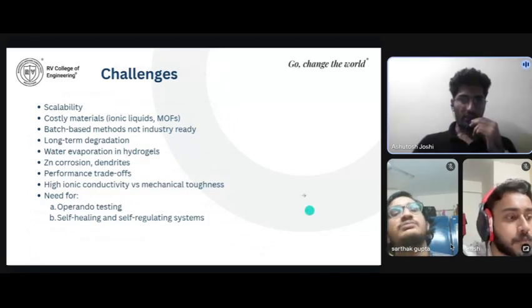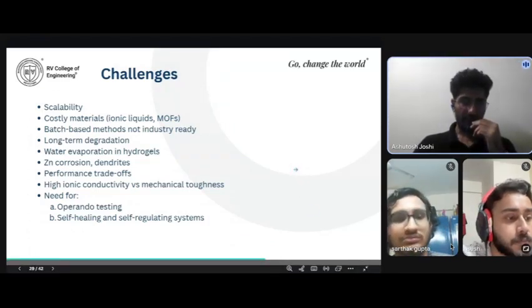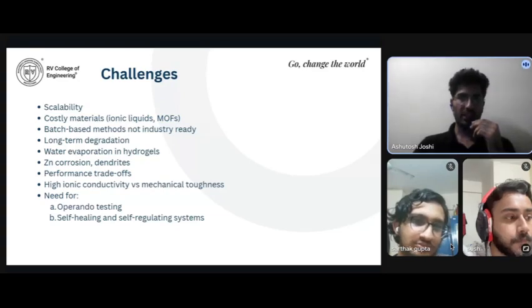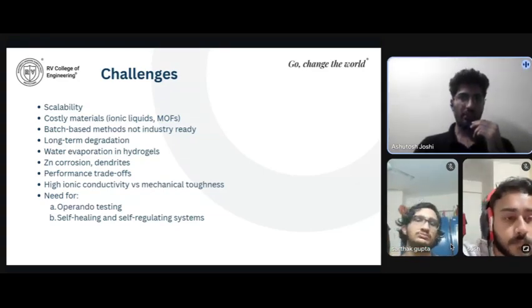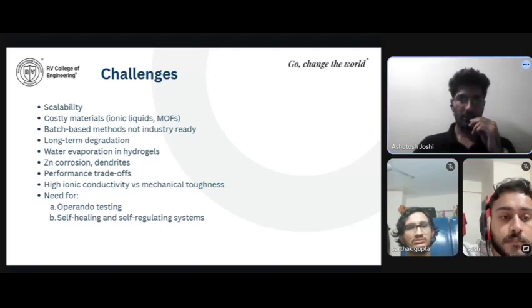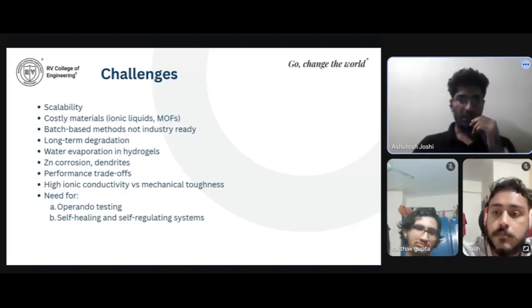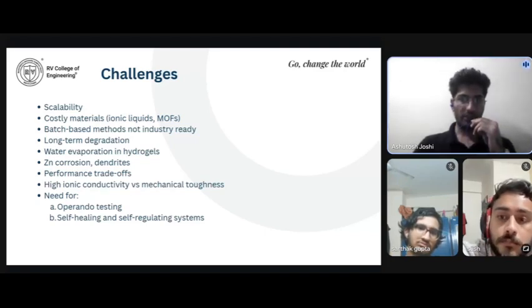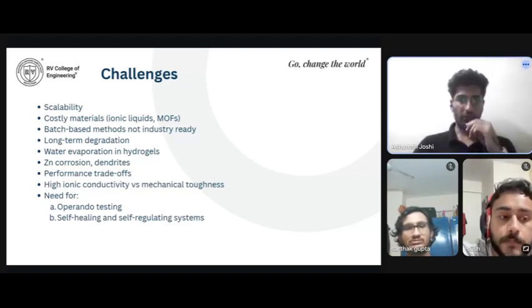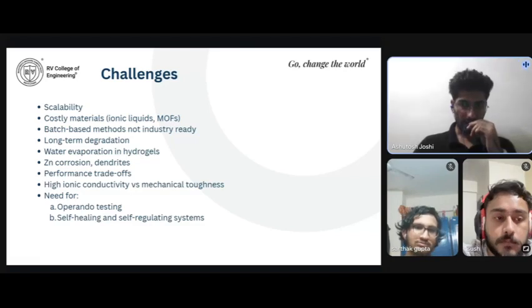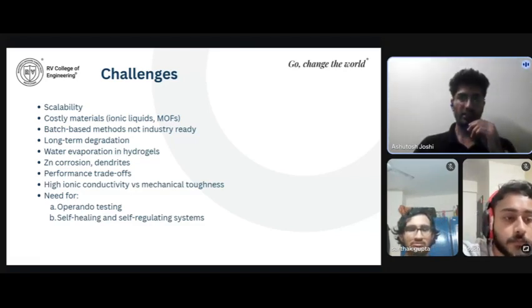So here are some challenges of QSs. First, scalability. Most QSs use expensive materials such as ionic liquids or metal organic frameworks. Currently, manufacturing methods are often batch-based, making them unsuitable for mass production. Long-term stability: water evaporation in hydrogel-based QSs limits their shelf life. Zinc dendrite growth and corrosion remain significant issues, especially in zinc-based systems. Performance trade-off: there is often a compromise between high ionic conductivity and mechanical robustness. Stretchable QSs may lack ionic pathways, while rigid ones resist deformation.